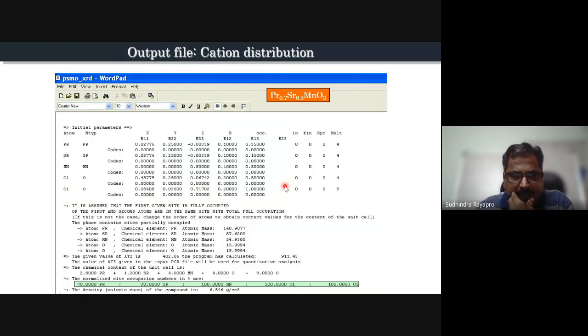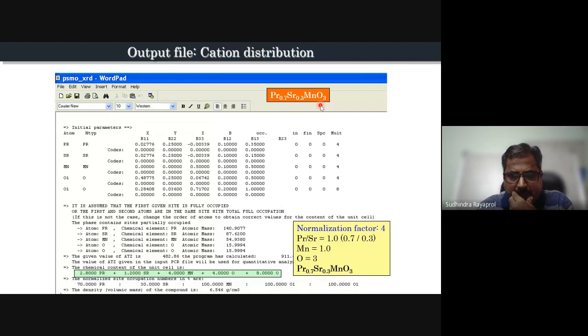So accordingly, once I substitute that in the PCR file, this is the site occupation numbers which comes in the output file, which shows that praseodymium is 70% occupied, strontium is 30%, manganese is fully occupied, so are the oxygen sites. So this is exactly what we wanted, that praseodymium, strontium should be 70-30 and the rest are fully occupied. So just to do a back-of-the-envelope calculation, you can actually find out that this is as per the stoichiometry.